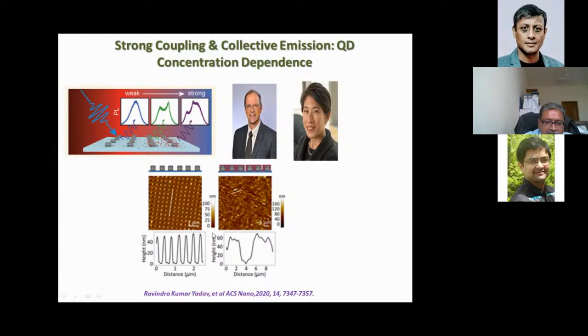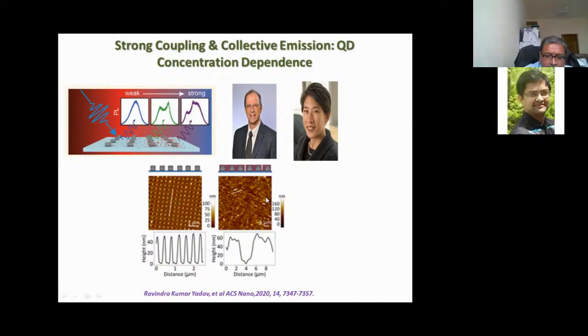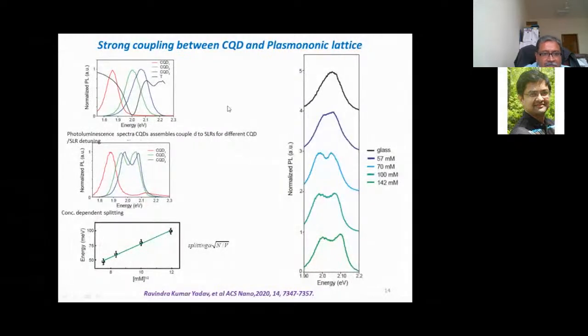You see this is the AFM image of the pristine template, these cylinder arrays. Then we can coat them with this quantum dot. Now instead of one, we have a very compact layer, and we can vary the concentration, or the density, or the thickness, so that we can do it in a very scalable manner. We look at that and explore what these different regimes are. For example, can we get into the strong coupling regime and so on. That's something that I'm going to talk about.